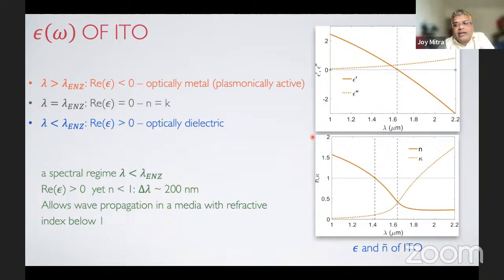But before I go into that, let me again reiterate that for wavelengths above lambda ENZ, it is optically a metal, and therefore it supports surface plasmons and is plasmonically active. Below lambda ENZ, it is optically a dielectric with the real part of the permittivity being positive. And what is seen here is that if you look at the refractive index, there is a very interesting regime in the center, which is colored in green.